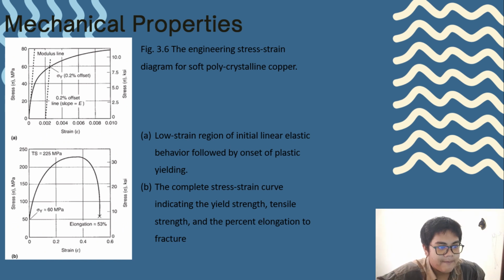In the initial portion of the plot, the lateral contraction of the specimen is distributed along the entire gauge length. The specimen is therefore so small that the nominal and true stress are almost identical, not the same but identical. But in the latter portion of the test, necking of a tensile specimen occurs, that is, straining begins to concentrate near the region where the fracture will eventually occur. This necking can often be so pronounced that the nominal stress will decrease upon additional loading, as shown in figure 3.6b, even though the true stress continues to increase until fracture occurs.